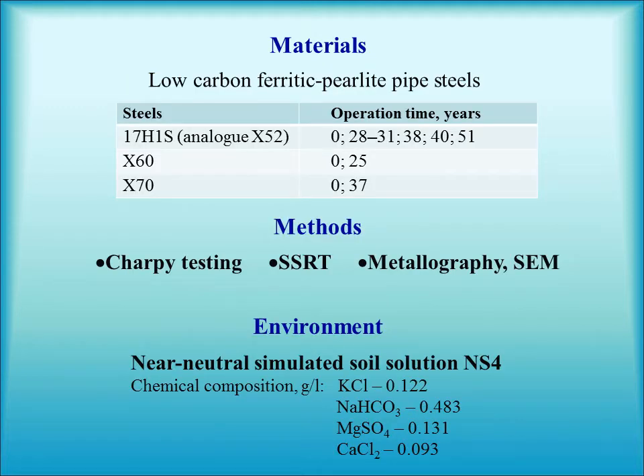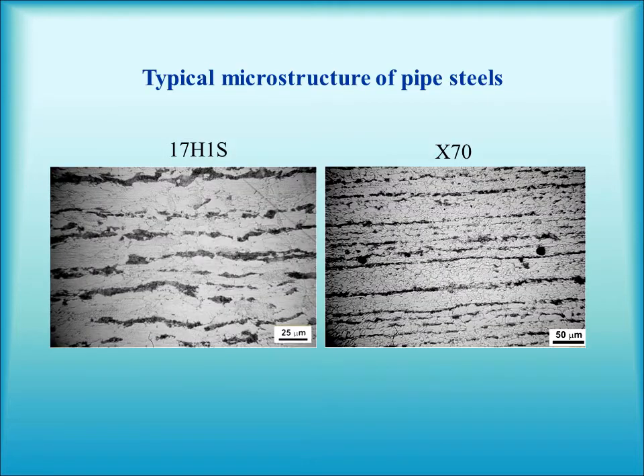The object of our research are pipe steels with different strength and time of operation from 25 to 51 years. Typical microstructure of these steels is the following. We can see ferritic grain layers alternating with strips of perlite, which are noticeably thinner, especially in the steel X70. Such texture is concerned with the rolling production process.